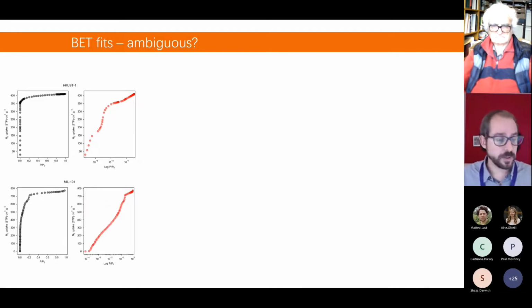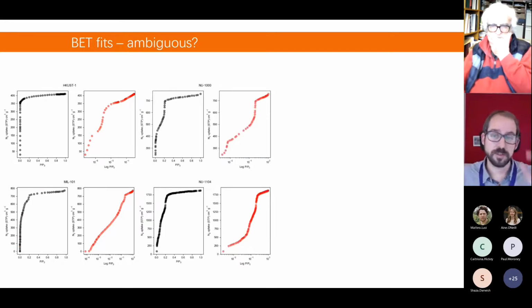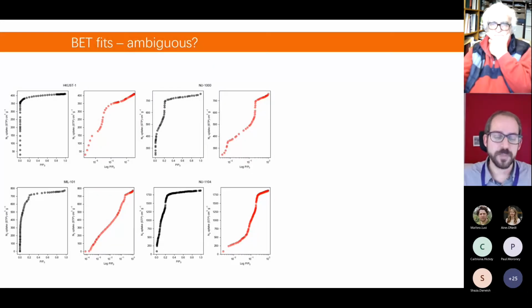That was for HKUST-1, a microporous material. For MIL-101, a mesoporous material, again, a lot of different issues on the isotherms. If we go to something more complex like NU-1000, yeah, definitely you can see very, very clear steps. And if you go to something like NU-1104, you can see that even on the linear representation, the isotherm has not a typical type 1, type 4 isotherm. It's something a little bit weird, but you have something that is increasing slowly again and again.